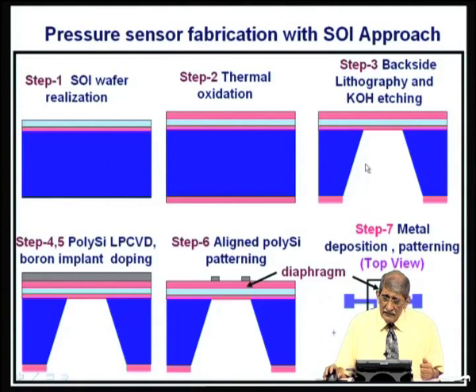The advantage of this is KOH etching will etch the silicon anisotropically, but its etch rate of oxide is very small. So, when it reaches this oxide, the etching automatically stops. So, what you have got is a membrane here whose thickness is that of the starting SOI layer thickness, that is the merit. Automatically you get a 10 micron thickness if I had a 10 micron thick SOI layer. So, now on this SOI layer, you grow oxide on the top of that, it is already there, use this layer now to realize your membrane.